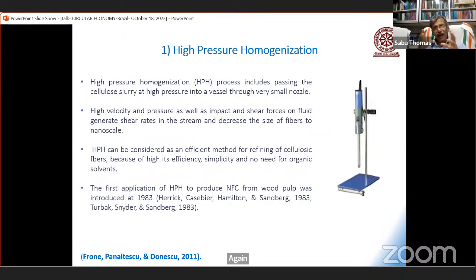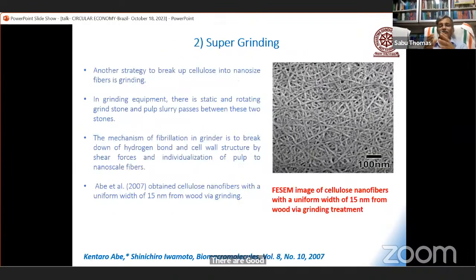So if you look at the high pressure homogenization process, what is being done is passing the cellulose slurry. You make the cellulose slurry and pass it at high pressure into a vessel at high velocity. Because of the high velocity and pressure, the nanofibers are separated. There are commercial instruments available now for the homogenization process.